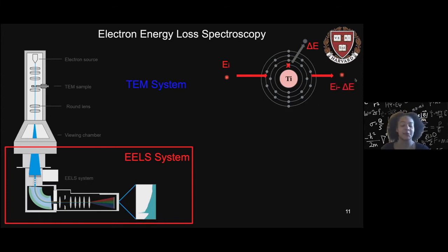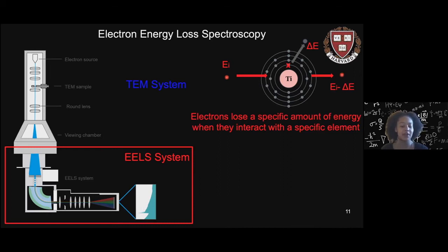By taking the difference between the final energy and the initial energy, we're able to measure exactly how much energy this electron lost. Now, what's key here is that electrons lose a specific amount of energy when they interact with a specific element. So if we measure a certain amount of energy an electron loses, we're able to determine whether it collided with a titanium atom versus a carbon atom, for example. If one finds a larger than expected number of electrons that come through the material with, say, 285 electron volts less energy than when they entered the material, this is approximately the amount of energy required to knock off the inner shell electron from a carbon atom. So this could be evidence that there's a significant amount of carbon in our sample.